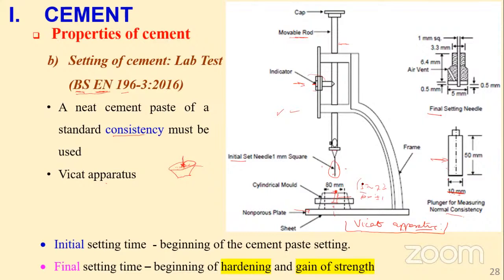If it's below this, maybe it's penetrated 3 millimeters, then it's too hard. Not enough water, so it's not of standard consistency. You need to add more water. If it goes beyond, let's say 8 or 9 millimeters, then still it's not of standard consistency. We may need to add more cement to make it a little bit stiffer.